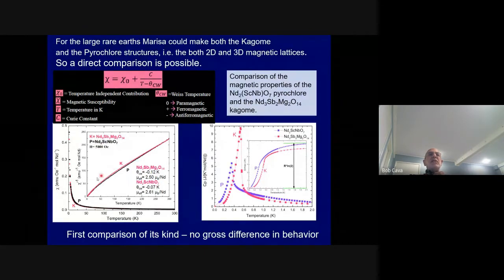And you can see this is the temperature dependence of the magnetic susceptibility and the temperature dependence of the inverse magnetic susceptibility versus temperature. They almost are no different. So basically, from a large scale view, the Kagome and the pyrochlore are extremely similar. And the Curie-Weiss temperatures are ridiculously low, which will get us to the next part of the talk. But the magnetic moments are similar. The Curie-Weiss temperature, which is a measure of the interactions, is really, really low.